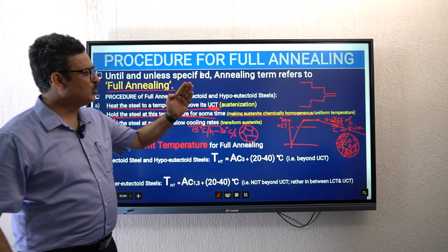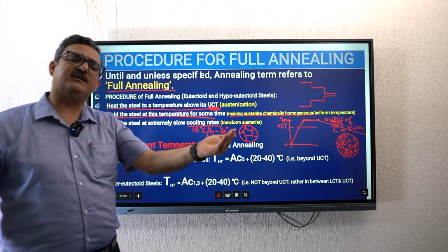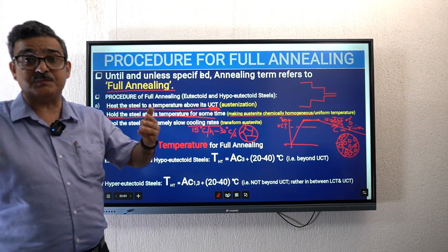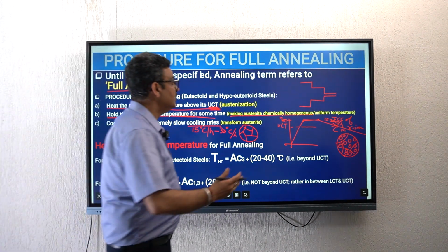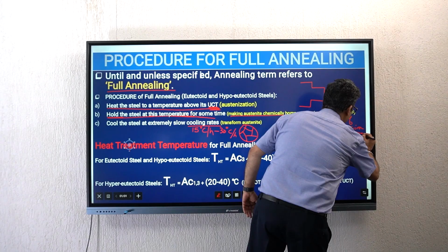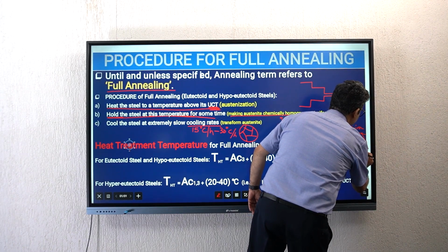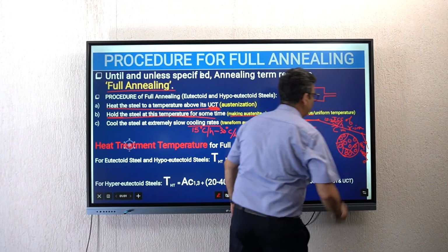जैसे ही austenite टूटकर उसने जो phases बनाने थे, 100% austenite टूट गया, कोई ज़रूरत अब स्लो कूलिंग की नहीं है, क्योंकि इसमें टाइम बहुत ज़्यादा लगता है। तो फ्रॉम देयर ऑन, अगर ट्रांसफॉर्मेशन कंप्लीट हो गई, आप यहाँ से तेज कूलिंग कर दो। कौन सी कूलिंग कर सकते हो, हद से हद एयर कूलिंग।